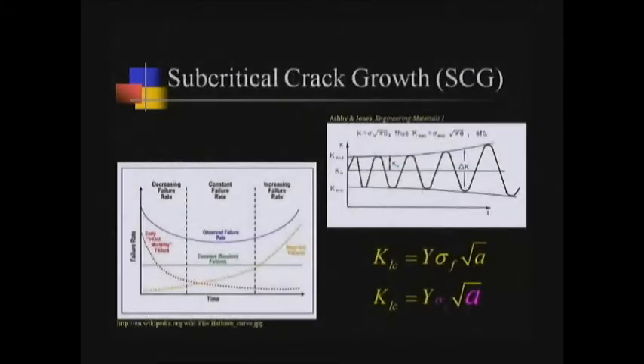Okay? And what happens as these cracks grow through the material over time? We may have mastication forces causing a cycling of stress, and because the stress intensity factor includes the stress, the stress intensity factor K will also cycle up and down during chewing. And we may have a constant chewing load causing a constant cycling of stress, constant amplitude stress in the material. However, as the crack grows, A becomes larger, and so even for a constant chewing load, the stress intensity factor gains higher and higher amplitude over time, eventually leading to failure.